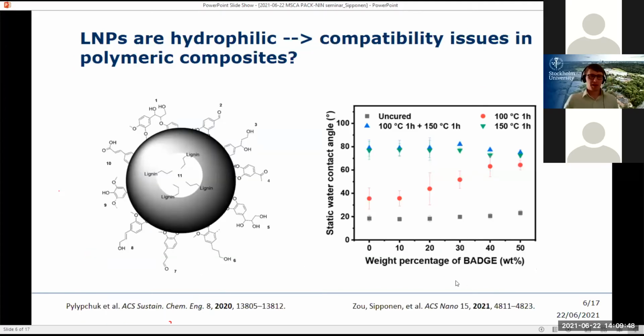As I said, these particles are very hydrophilic from the surfaces, and the chemical functionalities have been identified recently by liquid state NMR, or dispersion state NMR technique, which is a very nice advancement in the field. But what I want to highlight here is that, first of all, the hydrophobic nature of lignin has been very controversial. It's very regular to read papers that say that lignin is aromatic, so it equals that it's hydrophobic. But this is not, of course, true, at least for the isolated lignins.